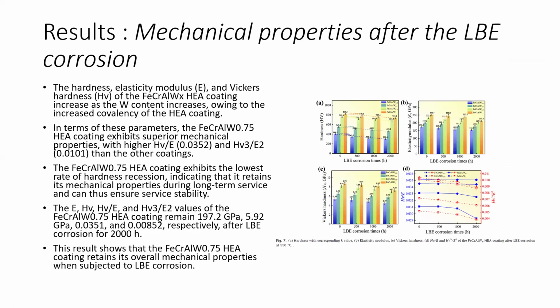And the results about mechanical properties after LBE corrosion. The hardness and elasticity modulus of the material coating increase as tungsten content increases, owing to the increased covalency of the coating. You can see from this figure. In terms of these parameters, the material coating exhibits superior mechanical properties, with higher H/E like 0.0352 and H cubed over E squared of 0.0101 than the other coatings.